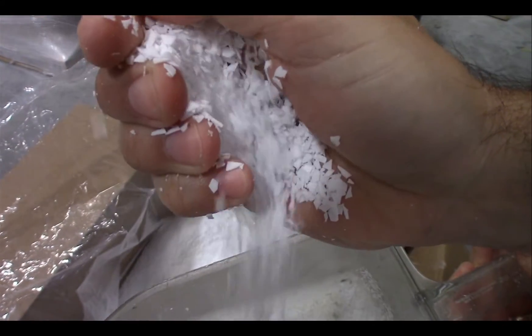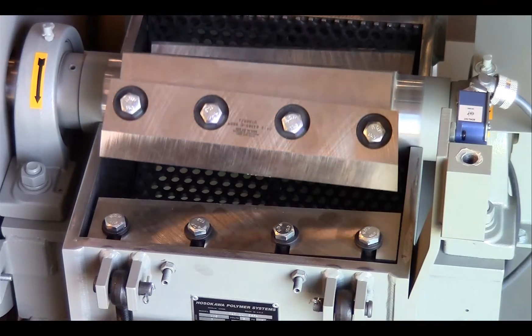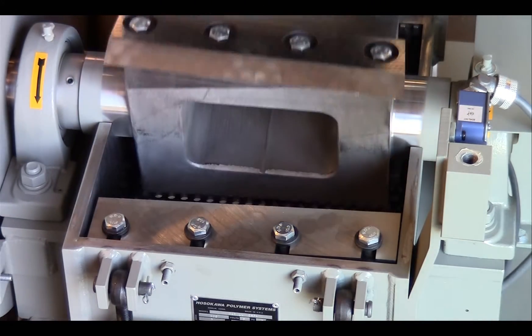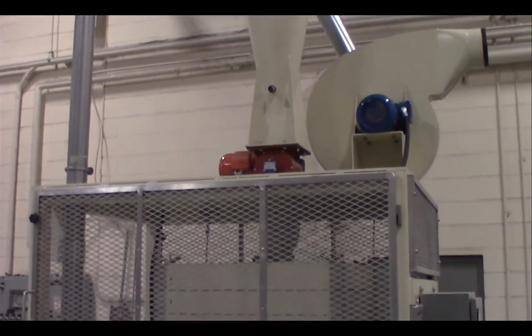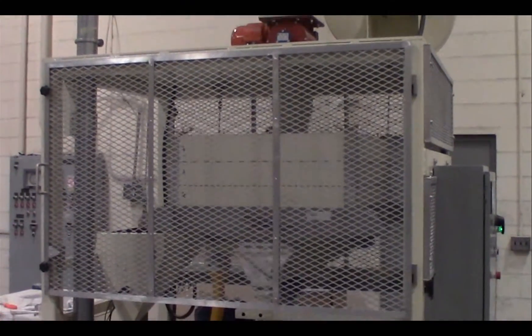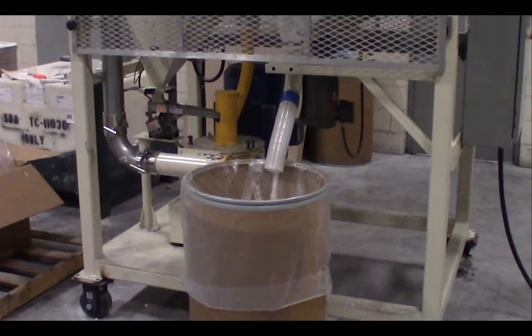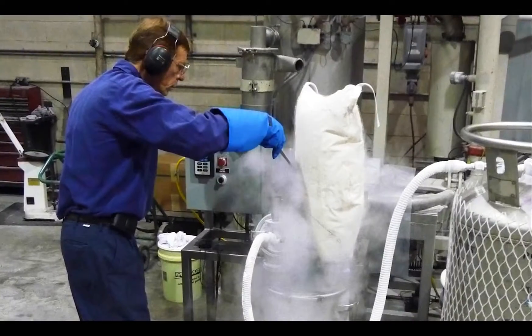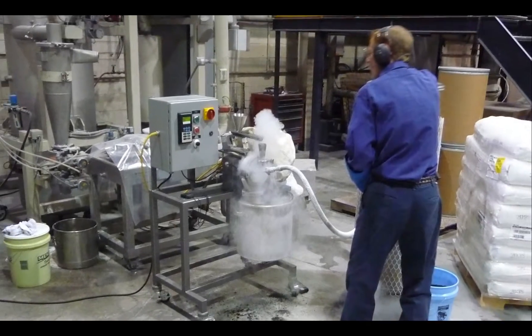The material being ground started as large polyethylene sheets that were granulated by Hosokawa's press-side granulator, which produced 4mm uniform dust-free chips. The customer would like to mill the material down to 100 mesh. Traditional size reduction techniques produce too much heat, which could damage or melt the material. Impact mills require liquid nitrogen to brittle the materials and prevent melting — liquid nitrogen can double or triple processing costs.